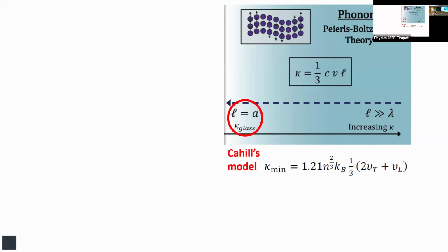So if I have a glassy system, that means there is absolutely no periodicity. Then the mean-free path, which gives me the thermal conductivity in terms of specific heat, sound velocity, and the mean-free path, the smallest value of mean-free path can be the interatomic distance. It is the minimum thermal conductivity. It's called the Ioffe-Regel limit. And this was worked out by Cahill, and that gave us the number, what the value should be, this minimum thermal conductivity, when the phonons are separated by interatomic separations. This is the lowest thermal conductivity.